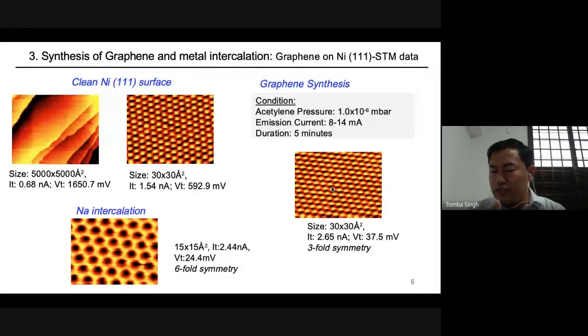Not only that, for the interaction, the distance between the two layers is also very important. If we increase the layer distance by introducing some atomic layer, the graphene can lift up from the surface. If we introduce an intercalated sodium layer between the graphene and the substrate, we can recover the six-fold symmetry of the graphene. Here you see the six-fold symmetry of the graphene in the STM topography. Yes, we see the six-fold symmetry on the surface, but whether the electronic and crystalline properties of the graphene are really recovered can be confirmed from the band structure.